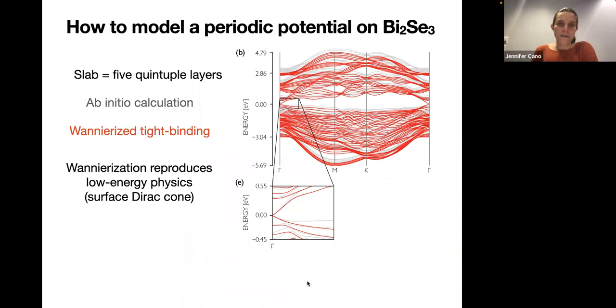So we now want to model this periodic potential on the surface of bismuth selenide. So how do we do this? We do an ab initio calculation. We make a slab consisting of 5 quintuple layers. The gray lines that you can see are from our ab initio slab calculation, and the red lines are from our tight binding model. At higher energies, they don't match each other, but we're interested in the low energy physics of the Dirac cone. Zooming into the physics around the Fermi level, you can see that the Dirac cone is very well captured by our tight binding model.